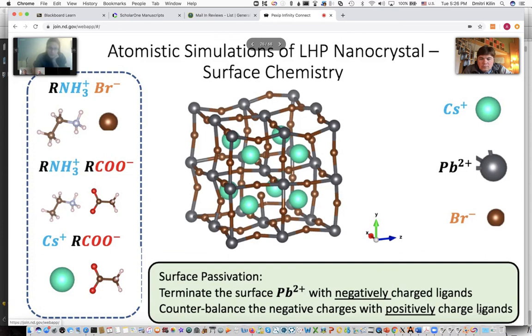So essentially there are 3 strategies you can use to passivate the surface. On this left-hand side on the top, you can have an ammonium bromide, where the bromides attach to the gray leads, and then the ammoniums take the place of cesium. We can have ammonium oleates, where these oleates, or these red ligands, attach to the lead, and ammoniums replace cesium. Or we can do cesium oleate, where the oleates bind to the lead, and the cesium take their normal position on the surface.